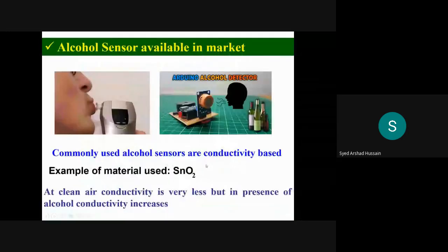Normally, the alcohol sensors available in the market are mainly conductivity or resistivity based. Actually, they use some material. It has very high resistivity in the absence of alcohol. When exposed to alcohol, the resistivity decreases, that is, the current flow through the material increases. And for this kind of system, you need some kind of battery, then a current meter, then you have to calibrate. So it needs a lot of devices, and of course it's costly. But in our system, only a piece of paper, you just observe the change in color, you can have an idea.